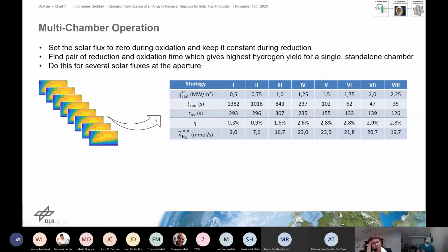Now, to analyze a multi-reactor operation, we made this investigation for a single reactor for different fluxes. So we chose different fluxes during reduction, and for these fluxes, we determined the best reduction durations and oxidation durations. As you can see, the reduction duration decreases with the flux. Here, I have to say that at the higher fluxes, the duration is actually limited by the material limit of the ceria, which is about 2000 Kelvin.